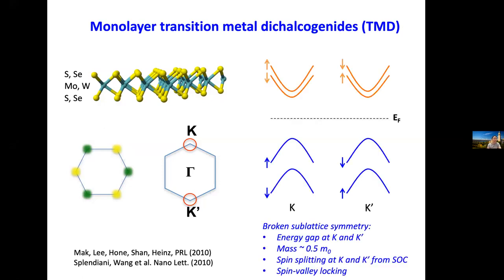It has been shown by us and colleagues a while ago that in the monolayer limit, these materials are direct gap semiconductors with the lowest energy gap located at the K and K prime points. The electron and hole masses are about half an electron mass. The bands are spin split by tens of millieV or hundreds of millieV for the conduction or valence band, and the spin and valley are locked to preserve time reversal symmetry.